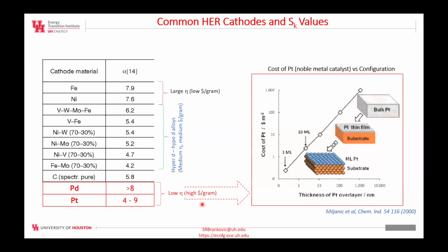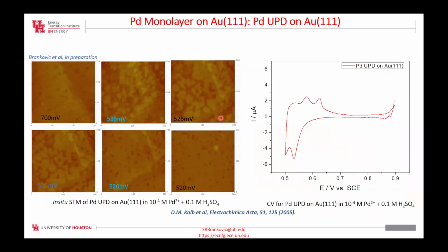And therefore, with our concept, we can actually go around this price per gram and use only a monolayer catalyst, whether it's platinum or palladium. Here we talk about palladium, and therefore the cost of this precious metal could be significantly reduced. So how do we create these palladium monolayers? We use gold. Just to give you an idea here, the palladium forms a perfect adsorption monolayer on gold through the process called UPD, or underpotential deposition.